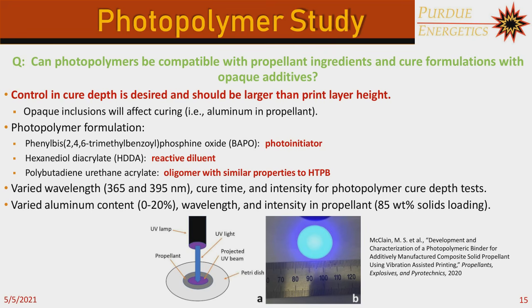There are many studies on how photopolymers cure and what the functional groups are, but not necessarily how things cure when you have a lot of particles in them. So in this study, we essentially used some commercial off-the-shelf photopolymer ingredients. Our photoinitiator was BAPO, which cures at 365 nanometers. We used a polybutadiene urethane acrylate, which is very viscous and sticky, but if you mix it with some sort of diluent, you can lower the viscosity and tailor it a little better.